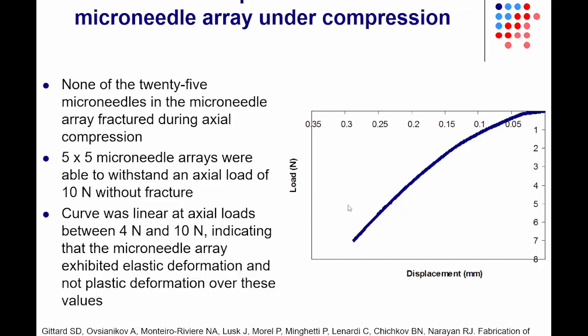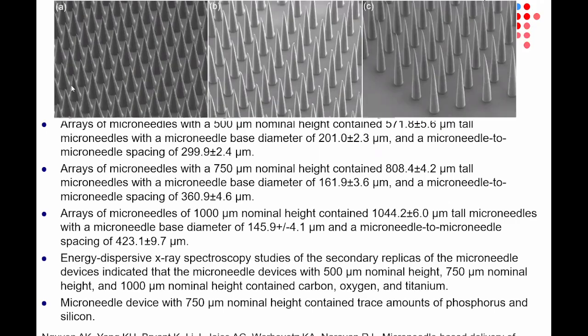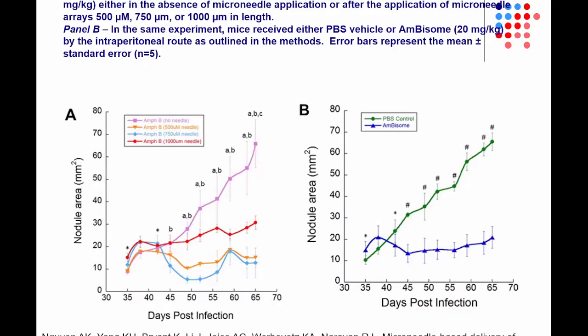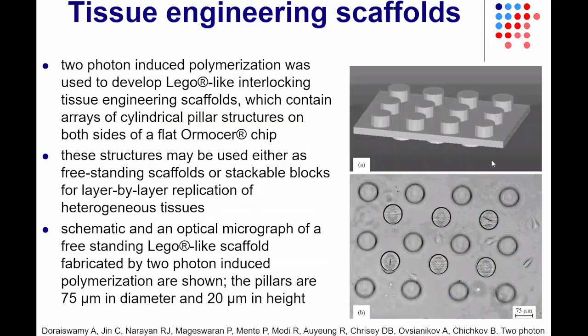And you can see here, we tested this system with mechanical testing, an Electroforce 3100 system. We're not able to fracture these solid microneedles. We then created dozens of replicas of these microneedles with heights of 500, 750, 1,000 micrometers tall. So these are basically microneedle arrays of solid microneedles. So it basically creates an array of pores in the skin. And then we use this to create pores in the skin and then deliver a drug, amphotericin B, that's used for treatment of cutaneous leishmaniasis. And so we were able to decrease the lesion size for the cutaneous leishmaniasis with this approach based on these 3D printed and then molded microneedles.